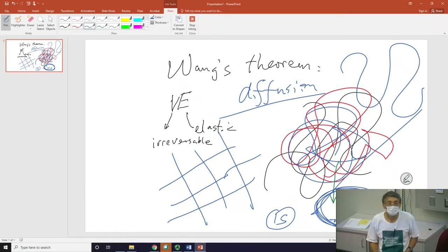And what do you mean? Or this is the whole 9 yards of the book. What do you mean it survives or not? Well, the only structure, as I casually said, is this uncrossability. And can I force them to lose that constraint between each other? If you do, you're destroying that elastic structure. If you're destroying the structure, isn't that when you stop having elastic response? And isn't that exactly the point of yield?